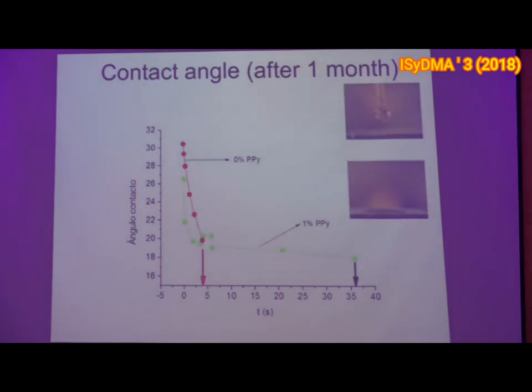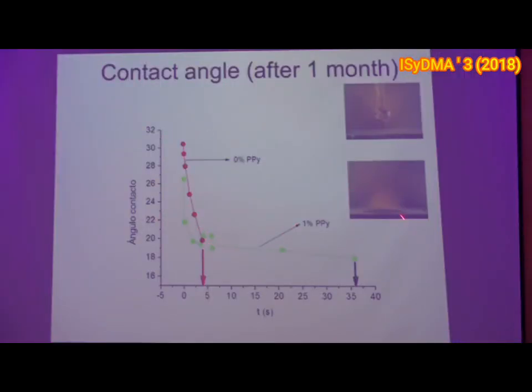So then we can see what happens when we made the measurements of the contact angle with the camera. This is a water drop that goes to this cement, and we calculate this angle. But what is interesting, we see here what happens with this red curve, this is without polypyrrole. After about 4 seconds, this drop disappears in the cement. So the cement is not impermeable. So we lose completely this drop in about 4 seconds.